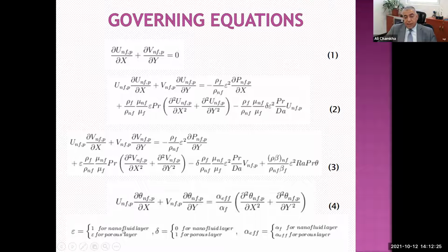And we put epsilon and delta in this to have a generalized model, depending on the region, since different equations dominate in different regions. So when epsilon is 1, it applies to the nanofluid layer. If it is kept as epsilon, it's for the porous layer. Same thing for delta: 0 for the nanofluid layer, and 1 for the porous layer. And for the thermal diffusivity, it's alpha_f for the nanofluid, alpha_eff for the porous layer.